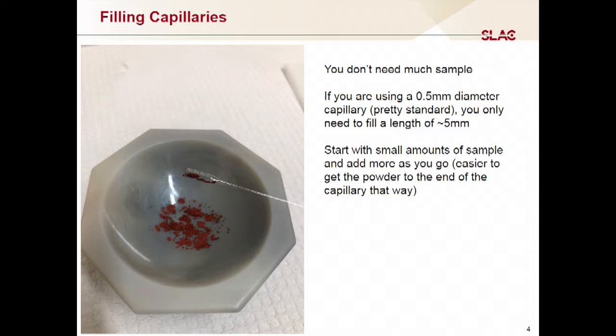So people often ask, how much material do you need to do a good powder diffraction measurement? Typically, people want this in something like milligrams. That's difficult because a milligram of something organic is a very different volume than a milligram of something like iron oxide. But if you think about the volume that you need, if you want to use a 0.5 millimeter diameter capillary, that's something that's pretty standard, you really only need to fill it up to a length of a couple of millimeters. And so you're not talking about really that much material to fill that volume.